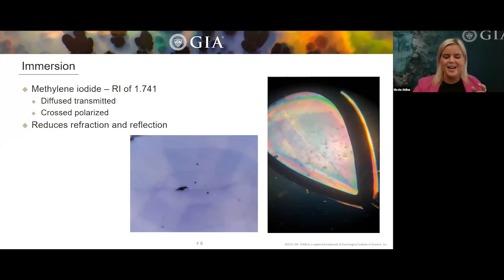So using a liquid that has a refractive index closer to the immersed stone will help reduce refraction and reflection to easily see the color zoning and growth structure. It's just going to hide those facets a little bit better for you. In the bottom middle picture is a titanium diffused sapphire in immersion using diffused transmitted light, and the blue color confined to the facet junctions is easily visible with the aid of immersion.